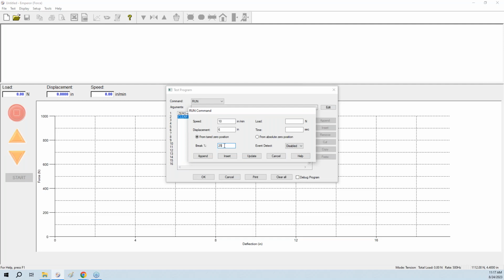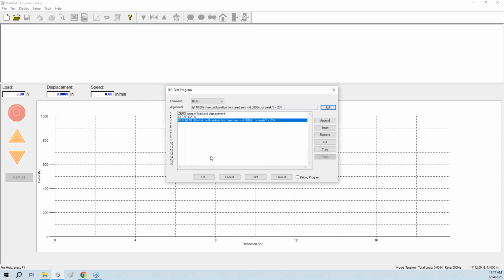Whereas if you're pulling on a stainless steel rod, when it snaps, it's likely going to drop from that 100 pounds or 100 newtons down to probably at least 5 newtons or all the way down to 0. In that case, you would use a higher value like 75% or 90% drop to capture that break if and when that actually occurs. So we're going to click append. That throws that in the line of programming. And then finally, we're going to select the end command and then throw that in there.